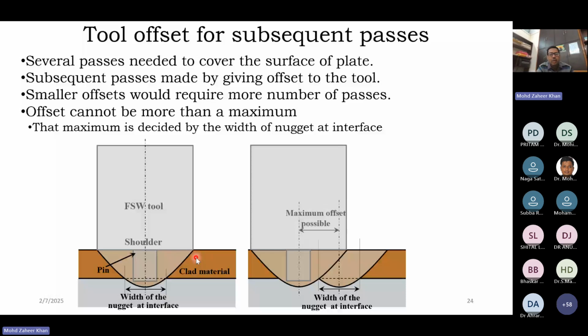Whenever one pass of cladding is carried out, the material gets processed and recrystallized in this parabolic zone. So this parabolic zone will have a width equal to the tool shoulder, and at the very other extreme it has a width equal to 0, and at the point where the substrate and the clad layer are in contact, this is the width up to which bonding has taken place. Whereas the region of the clad and substrate material outside this parabolic region has not joined. So if the offset is for a very large distance, larger than the maximum possible shown in this schematic, then there will be an unbonded region remaining over here. This unbonded region will lead to peeling off of the clad layer, and therefore the maximum amount of offset can be kept equal to only this.